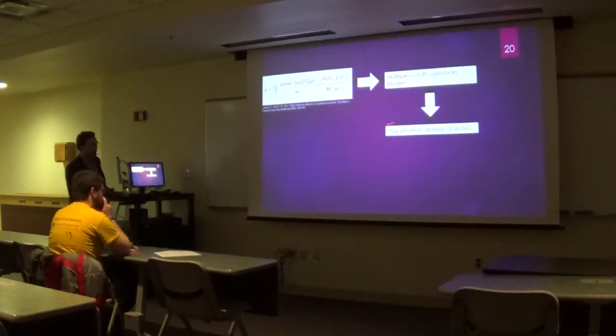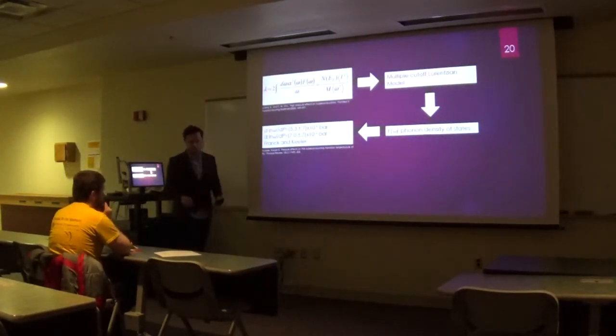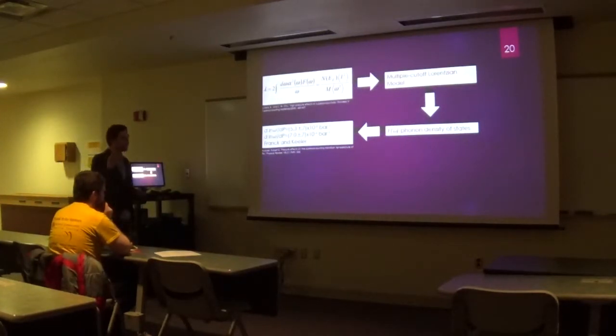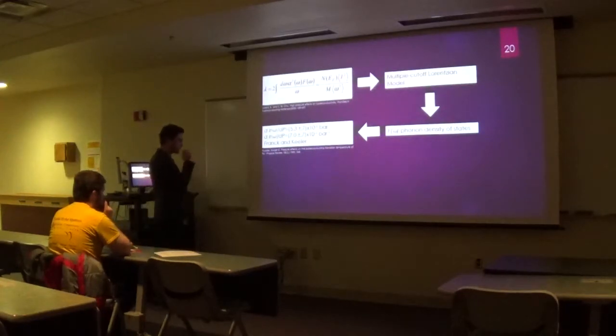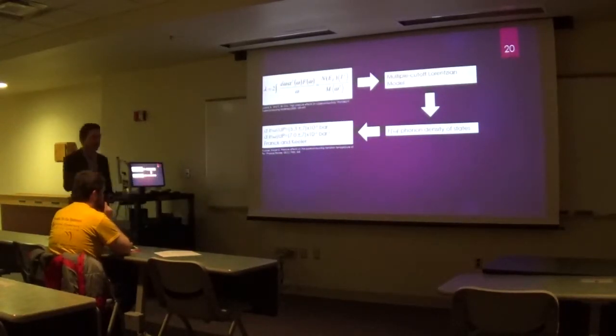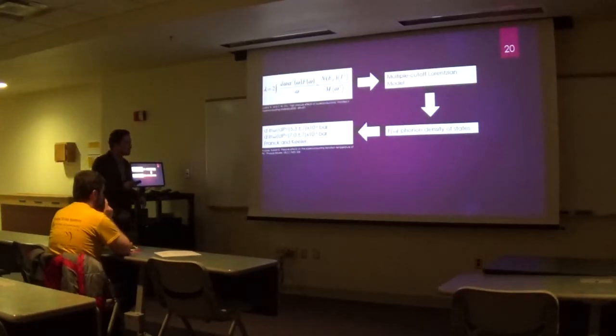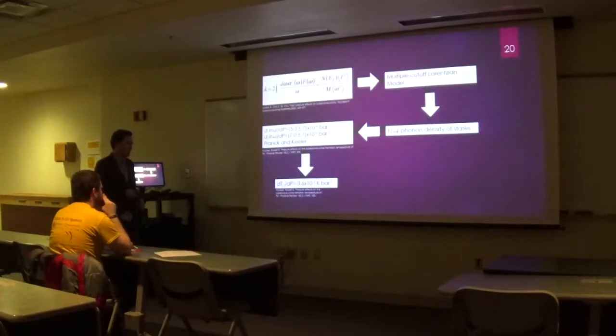The way we do this is we have to assume what is called the multiple cutoff Lorentzian model. It's just a big technical definition for manipulating this phonon density of states, or the population of phonons, and we can break it up into both transverse and longitudinal waves. If we think of our crystal lattice, it can vibrate a bunch of different ways, with a bunch of different wavelengths from phonons. Using the data by Frank and Keeler, we see that if we increase our pressure, we're going to be increasing our phonon frequency. So if we're increasing our phonon frequency, we're going to be decreasing the total amount of coupling between our electrons and phonons. This results in our negative pressure coefficient, or a change in critical temperature with respect to pressure.